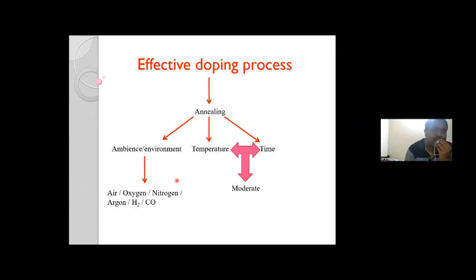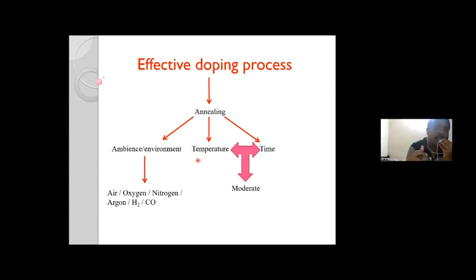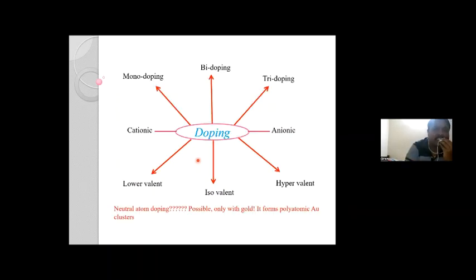For example, if you are doping zinc in titanium dioxide, as per the literature, you can use only 400 to 500 degrees Celsius. Beyond that, you observe the formation of zinc titanates. We must ensure that the ionic radius of the dopant as well as the annealing conditions are appropriate to result in a doped matrix, not a composite surface.